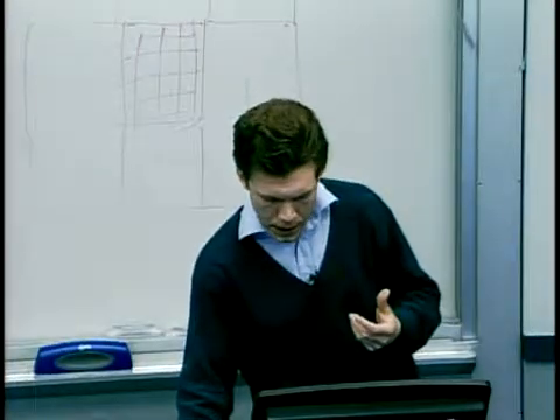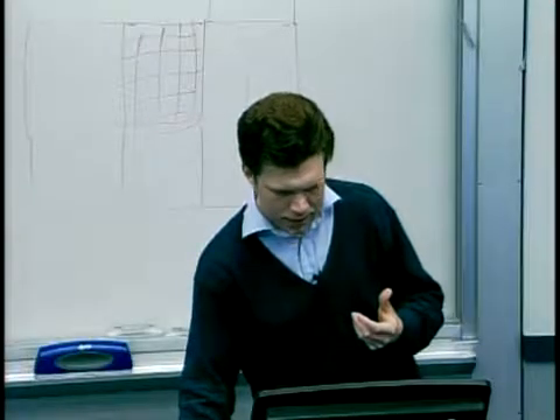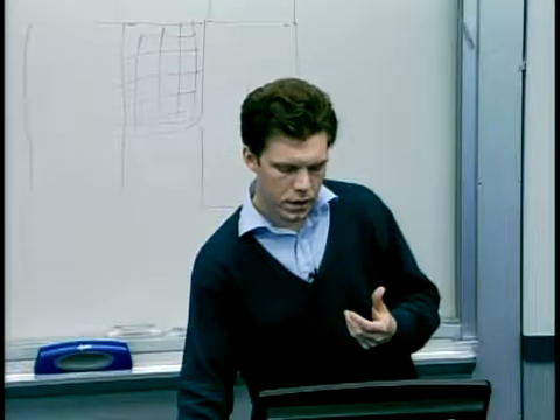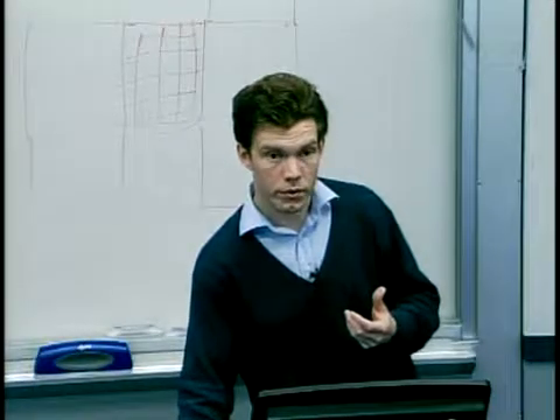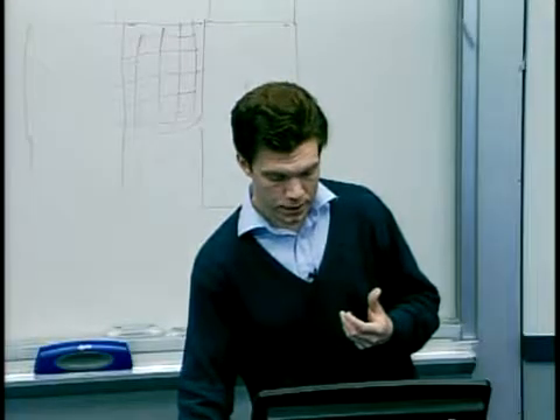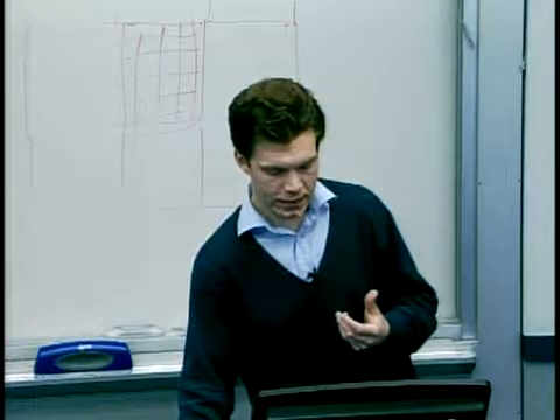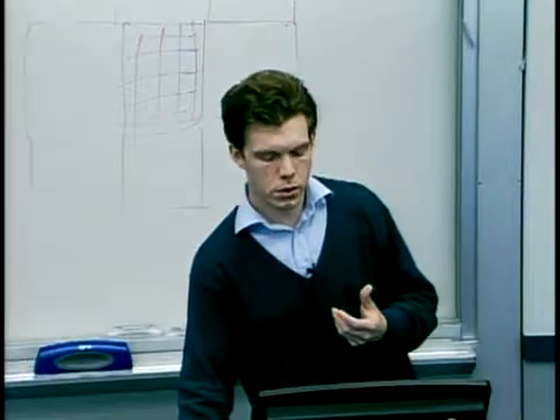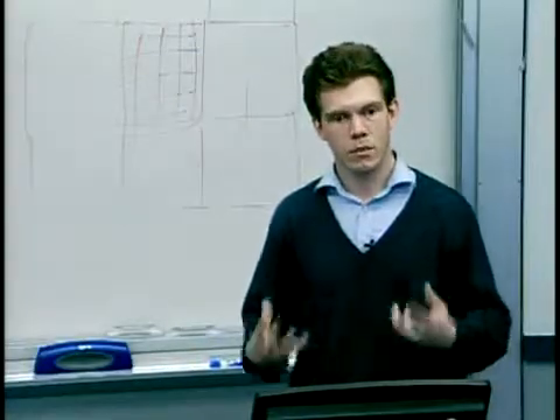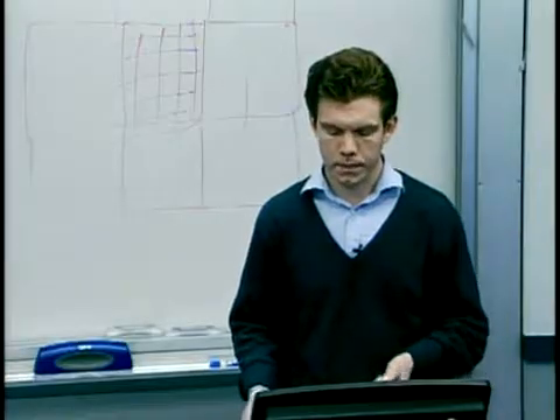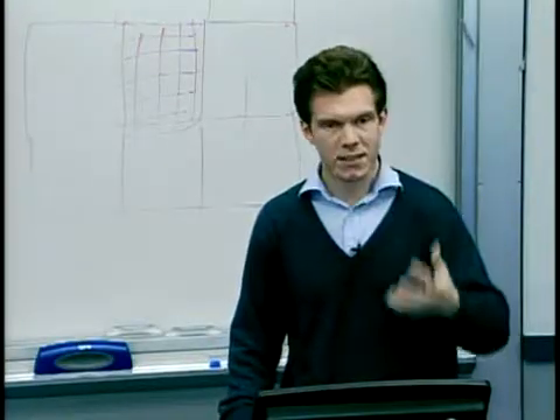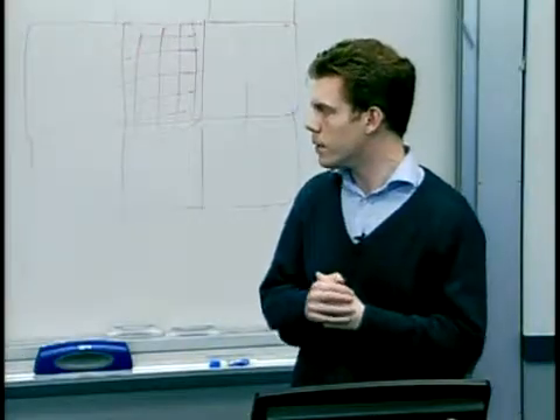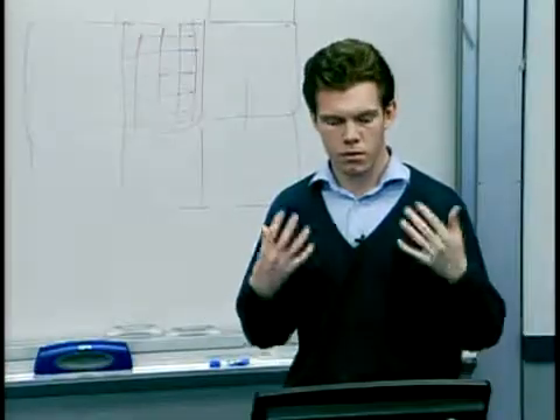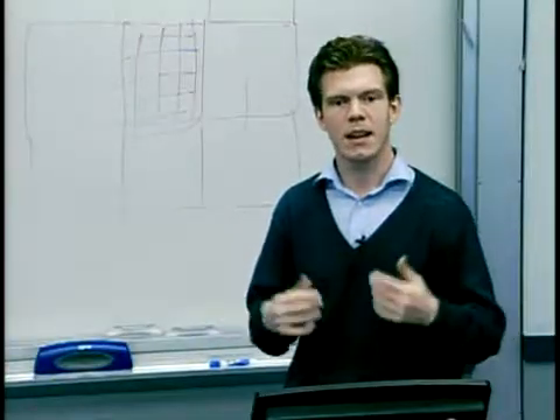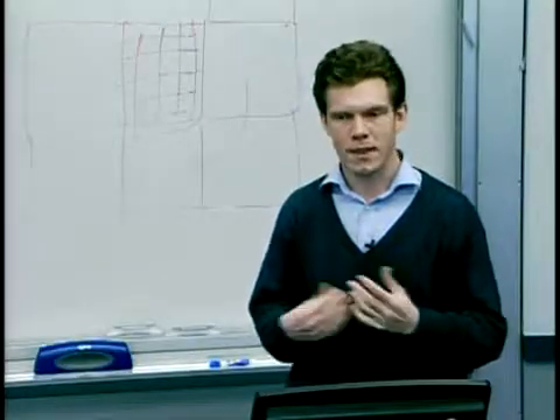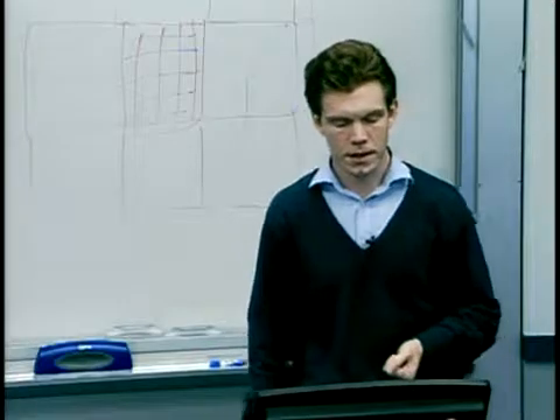You can see, for example, here, you're seeing many instances of a given trench diameter, but trenches that are closer to different patterns fill less far than those that are in the center of the patch. And this is all captured reasonably well by this rubbery model of the polymer. So it looks like we've got the basis here for doing efficient simulations. You can run that simulation in 20 seconds in MATLAB, and it's giving you, I think, probably 95% of the information a full finite element simulation would give you, as far as topography is concerned.